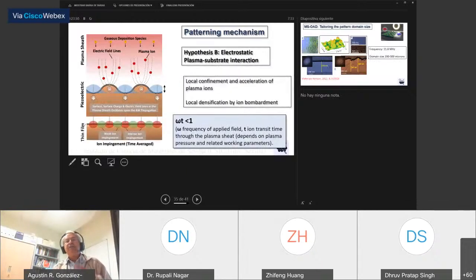So with that, we have arrived at our hypothesis of what the effects inducing this 2D patterning are. And the idea is that in magnetron sputtering, what we have is a plasma that, if we approach the substrate sufficiently close to the target, produces a plasma sheath on the surface of the substrate, a substrate which is oscillating, and not only oscillating, but also changing the polarity of the electric field in certain zones. While in other zones here, there is no change in the electrical polarization.